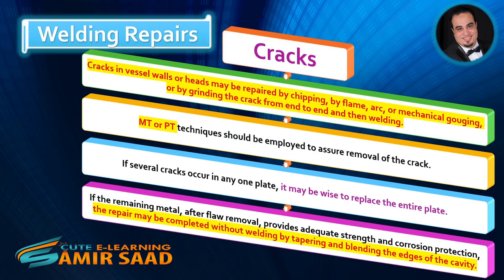Cracks in vessel walls or heads may be repaired by chipping, by flame, arc, or mechanical gouging, or by grinding the crack from end to end and then welding. MT or PT techniques should be employed to assure removal of the crack. If several cracks occur in any one plate, it may be wise to replace the entire plate. If the remaining metal, after flaw removal, provides adequate strength and corrosion protection, the repair may be completed without welding by tapering and blending the edges of the cavity.